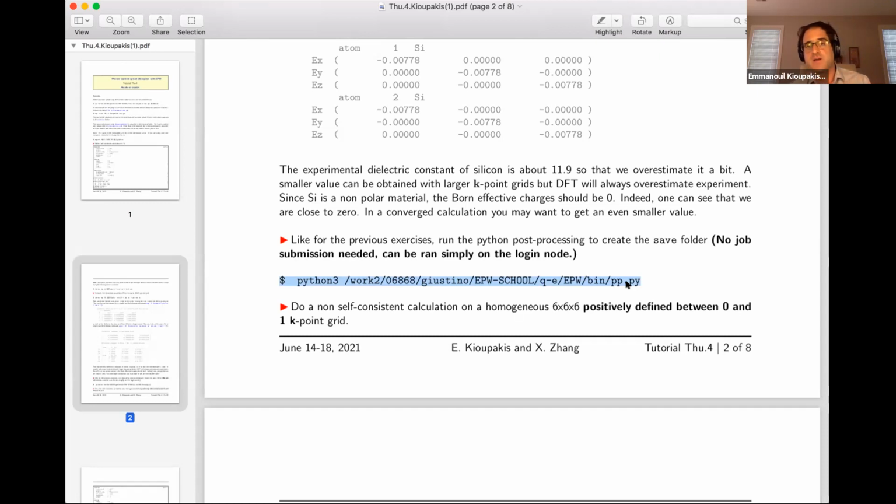In silicon, the conduction band minimum is at a low symmetry point, so it may not be part of your grid. You'll have a point close to the minimum, but it won't be right at the minimum. So you need to first do an interpolation with EPW, find where the minimum eigenvalues occur, and that will tell you what the minimum gap is, and that will tell you what photon energies you need for absorption. Yes, so you need a good interpolation to be able to find the band gaps accurately.